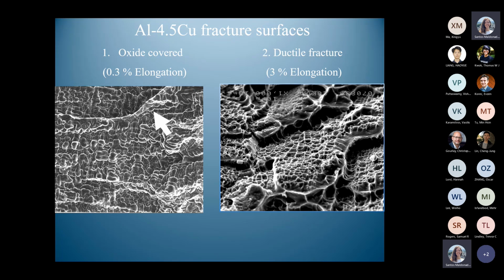Whereas here, in this ductile dimple structure, at the bottom of every dimple there's a silicon particle which wouldn't have fractured except that it grew on a bifilm. You remember the bifilm had the center unbonded and dry, but the outside was in perfect atomic contact. And what happens is that particles, like silicon particles in the aluminium alloy, nucleate and grow on the bifilm, on the wetted surfaces. So they can grow on both sides of these things.